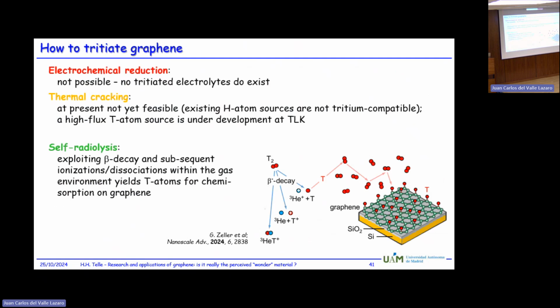So basically, the way we do that is the two methods I discussed previously, electrochemical or thermal generation of the hydrogenation or tritiation does not work, because one, for the electrochemical path, there are no electrolytes available, at least not in that large amount you need to do a tritiation in a bath. And the second is thermal cracking. In principle, it's possible, but in practice not, because all the commercial instrumentation is not compatible with tritium. So it has, for example, polymer O-rings, which will be attacked by tritium and so on.